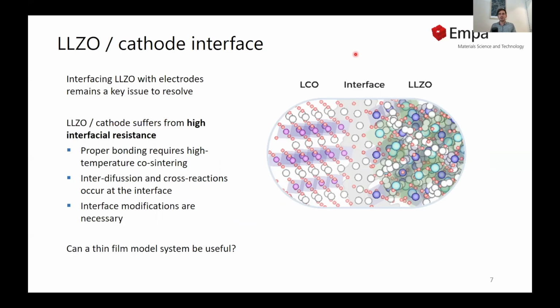Now let's talk about the LLZO/cathode interface. It is well known in the solid-state battery community that the interfaces of oxide materials with the electrodes are very problematic. For example, the LLZO/cathode interface suffers from high interface resistances because in order to form a proper bonding between both oxide materials, LLZO and lithium cobalt oxide, for example, one needs high temperature co-sintering.